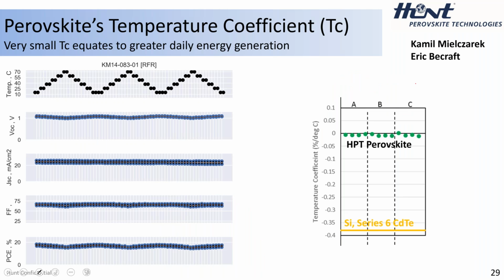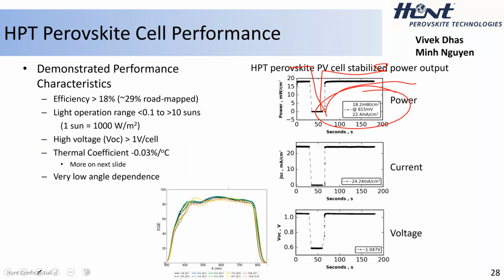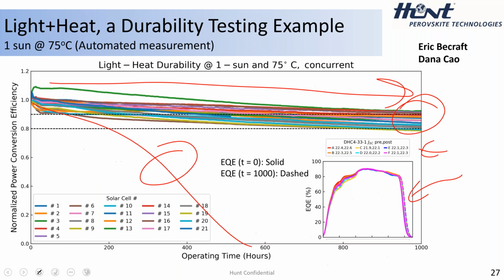So we've built a large number of systems. I didn't actually mention this earlier. In our lab, bespoke systems, not really bespoke, but bespoke to PV, really, not to perovskite. But we have these specific systems that we've built to test durability. We've taken an architecture and other similar architectures and developed other systems. So the one that I showed previously is a temperature-controlled stage with persistent white light and electronics, so we can make constant, regular measurements over a 24-hour period, over 1,000 hours. So about 6 weeks worth of time, but everything is concurrent and persistent.